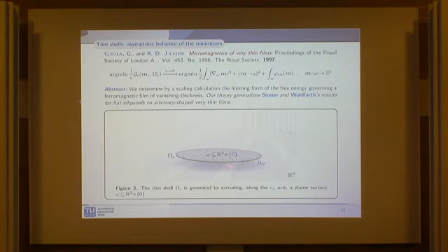Actually, if you don't have anisotropy, it's clear that the whole configuration will be uniform and in-plane, because this positive quantity will be 0, and m dot e_z will be 0. And they generalized what was already known for ellipsoids, through the works of Stoner and Wohlfarth.